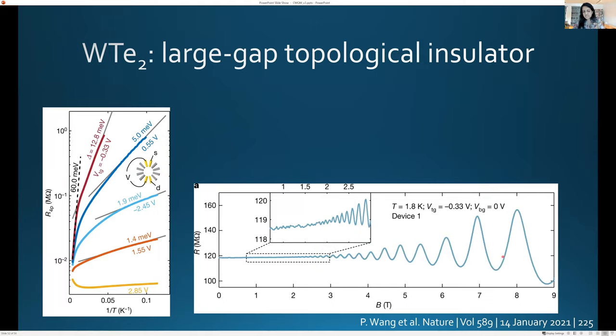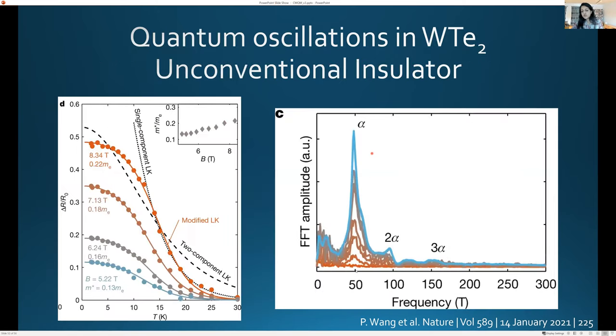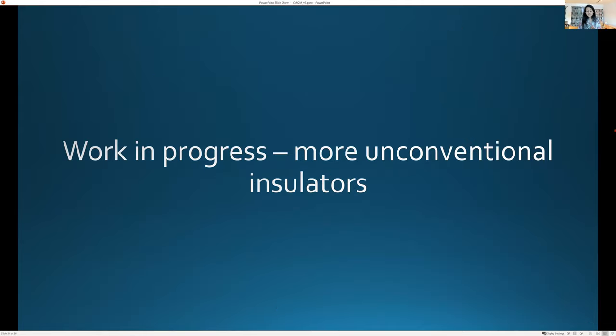So they see quantum oscillations in this case, in the resistivity that they have reported, and they associate them with the bulk. So this is a very low quantum oscillation frequency, I guess. Oh, here someone asked about harmonics, I guess. They report these to be harmonics. I'm not sure if I would identify them as frequencies. But I think the main thing they're reporting is very low frequency quantum oscillations in 1/B with a fairly light mass.